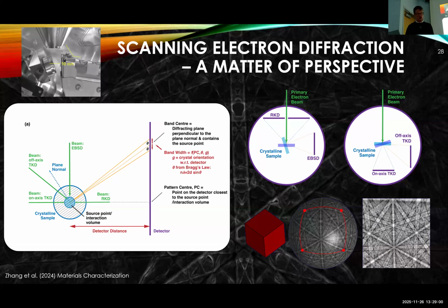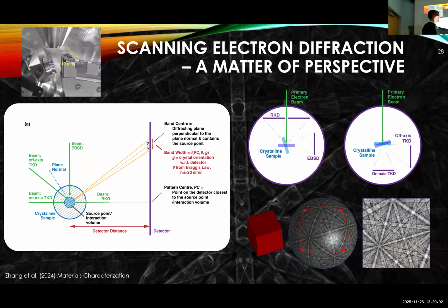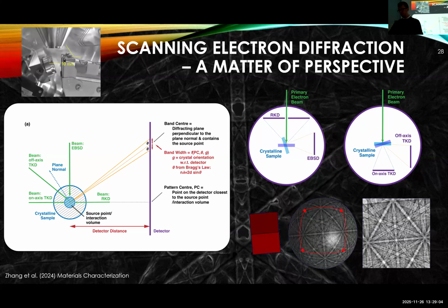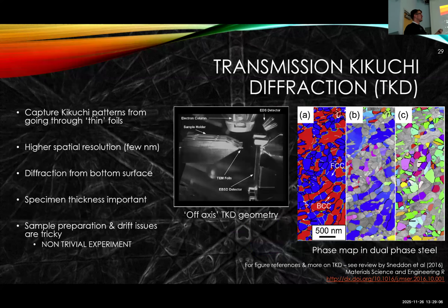And EBSD is just a matter of geometry. If we can get a pattern, we can work out what the orientation is. So this is the transmission Kikuchi diffraction as first introduced. Well, it was by Keller and Geis. There's a really lovely review by Sneddon from the Australians in 2016. And this enables us to get between 2 and 4 nanometer step size in a TEM lamella. Very accessible because an SEM is significantly cheaper to operate than a TEM, just in terms of training, access, and a whole range of bits and pieces.